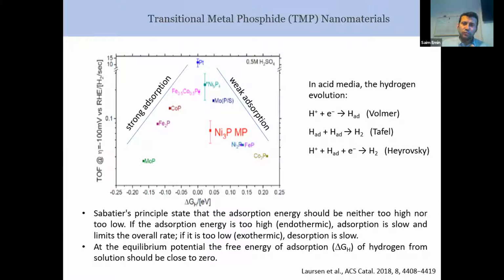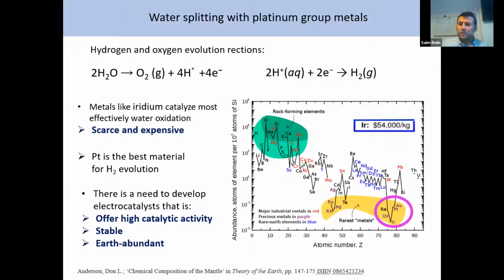However, by tuning the composition of materials, it's also possible to tune the strength of adsorption and desorption which hydrogen will experience on the electrode surface, and design catalysts to eventually replace platinum. Platinum is very expensive. Platinum group metals, like rare metals, are very expensive. They can cost 30, 40, $50,000 per kg. Iridium is one of the very good materials, and ruthenium, for example, to oxidize water. Platinum and palladium are good for water reduction, let's say.